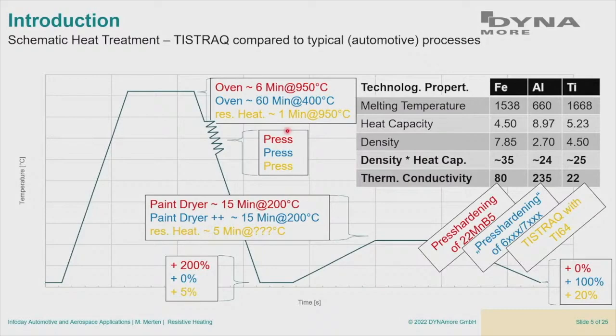Taking a coarse look at properties: when you do press hardening of steel, you get an increase in ultimate tensile strength of approximately 200% — from 500 to 1500 MPa. In aluminum you have almost nothing from the press hardening itself, just some solutes contributing to hardness. In titanium, there is also a martensitic transformation, but it only increases strength by 5%. The heat treatment at the end defines most of aluminum's properties — up to 100% depending on the alloy. In our titanium, we are talking about 20–50% based on literature data, which requires some measurement effort.